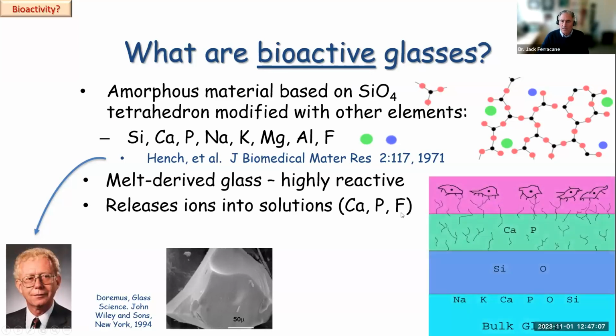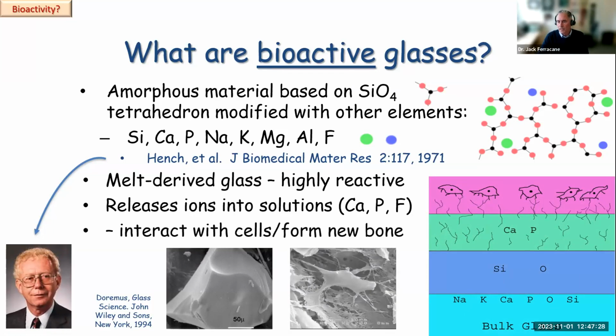And the main purpose of this was basically, if you have the bulk glass, you will get ion release and movement through the surface, leaving behind a silicon oxygen-rich surface, but depositing ions at the surface, which can begin to precipitate new mineral. And at the same time, interact with osteoblasts, which will then become actually embedded, their proteins being embedded within the new forming calcium phosphate, and form a bond to basically new bone as it forms. So the concept of bioactive here was really with respect to mineralization and bonding to bone.